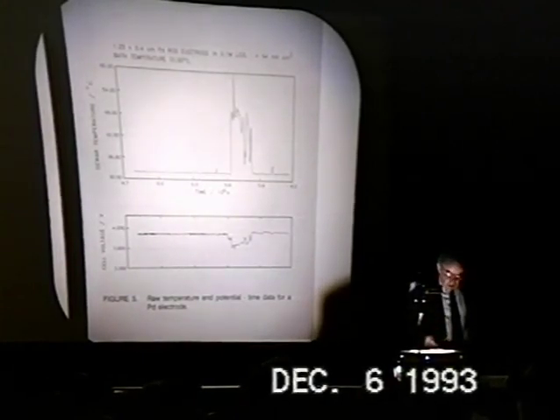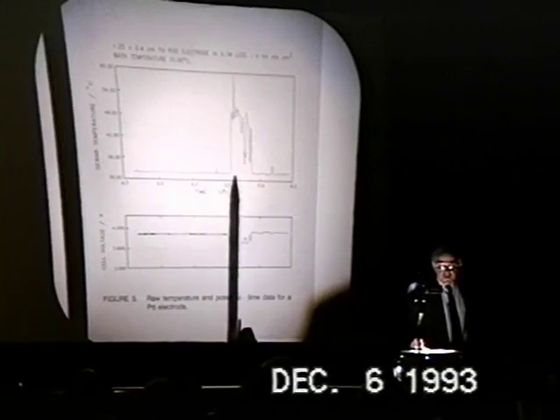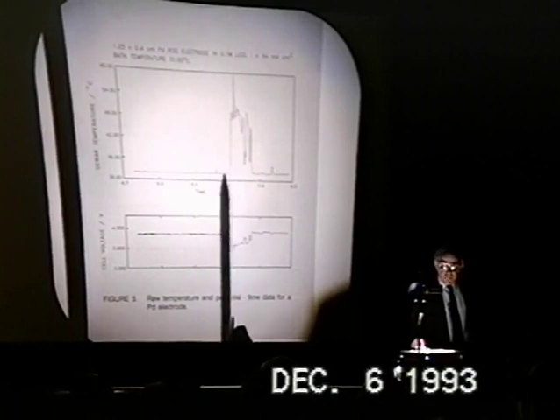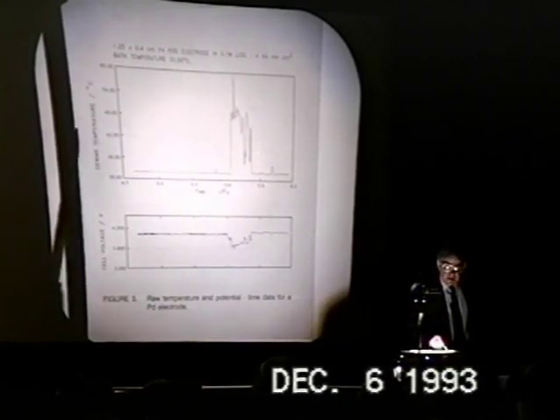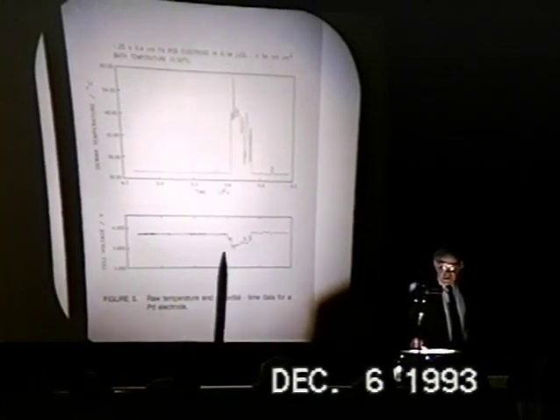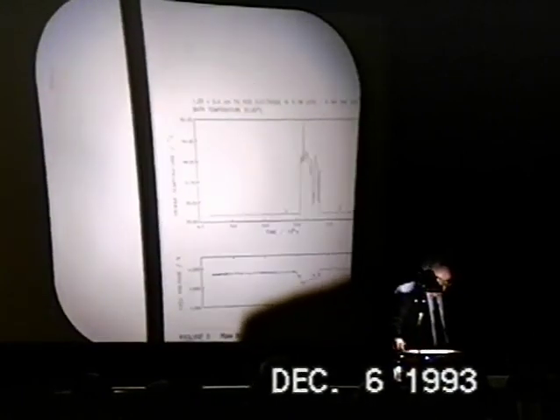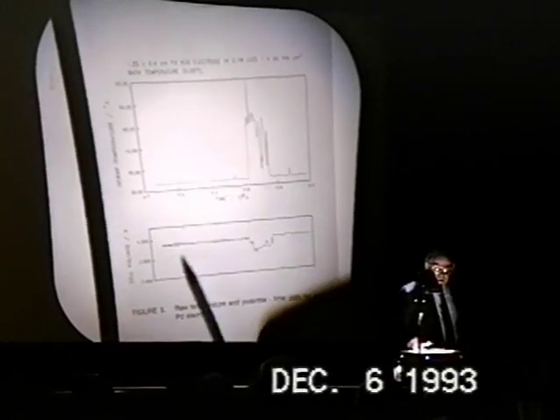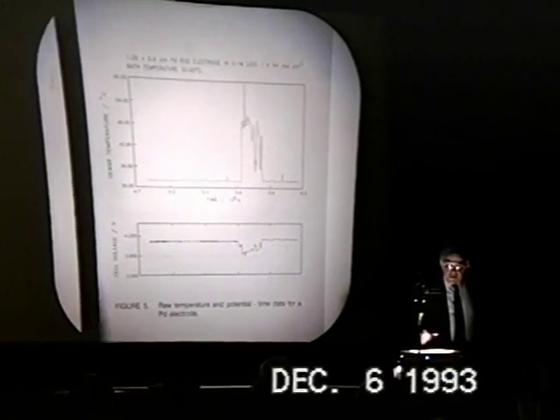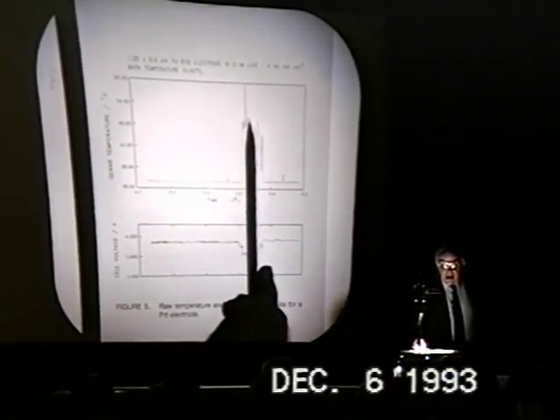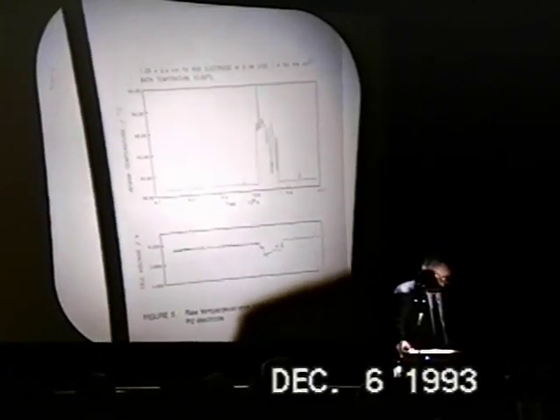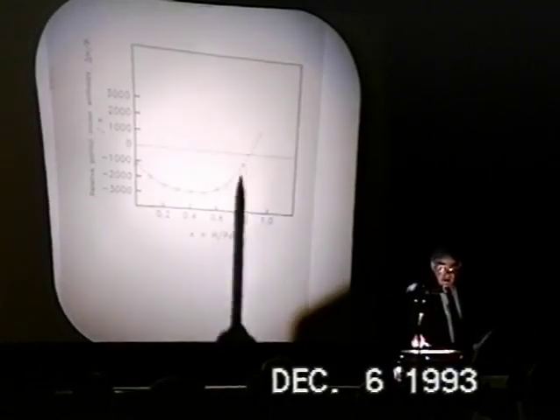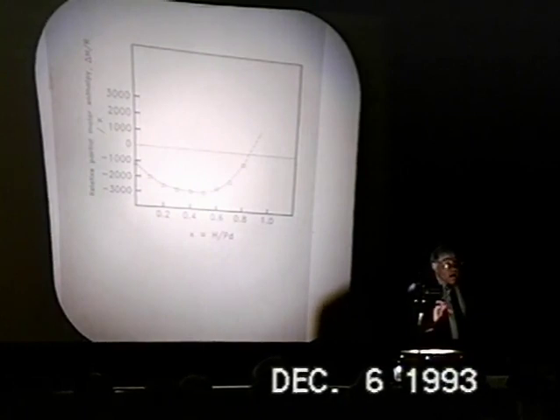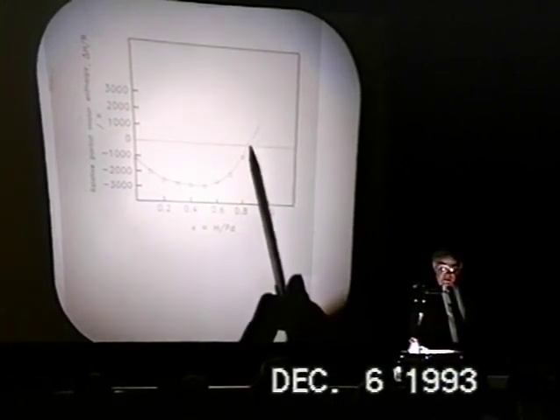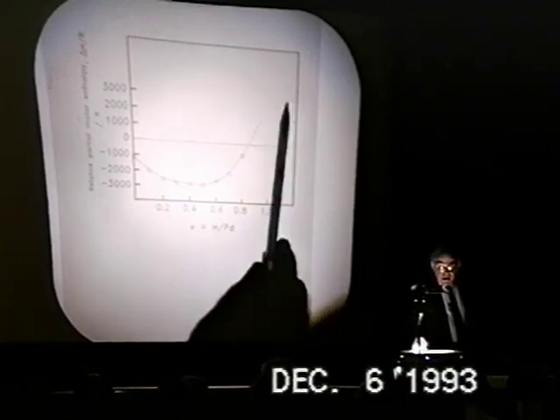Now, our search for high rates of enthalpy generation was directed by the fact that we had seen bursts. This is the cell temperature, raw data, with increases in the cell temperature and increases in the cell voltage, marking that we could achieve marked increases in the performance of the system. Although this was very inefficient in energy terms, we did achieve about 10 times more energy out of this state than the energy put in. So our search at that stage was focused very hard on whether we could achieve high rates of energy production at high temperature by crashing the system through an exo-endothermic transition and driving it to high temperature.